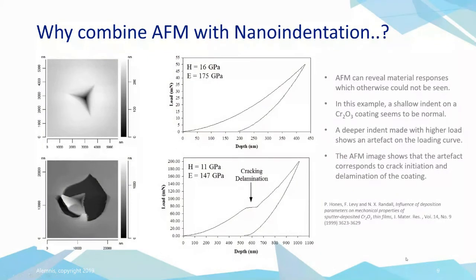Okay, also AFM can reveal material responses which otherwise we wouldn't see. So in the example here, this is a chromium oxide coating. The top curve and image show a low load indent. So this is up to 50 millinewtons. And you can see here that the indent looks pretty perfect. Now, if we go up to a much higher load, this is 200 millinewtons,